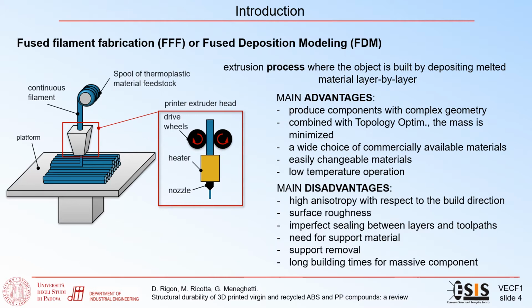A wide choice of commercially available materials, easily changeable materials, and also a low temperature operation. The main disadvantages of this process are high anisotropy with respect to the build direction, the surface quality of the component in the as-built condition, the imperfect sealing between layers and tool paths, and the necessity of support structures in some parts of the component. Finally, the process takes long times to produce a massive component.